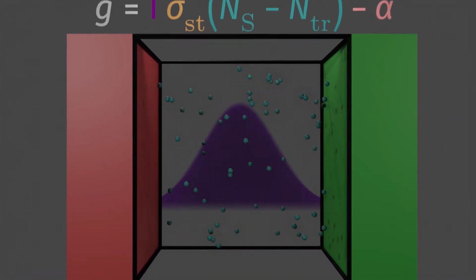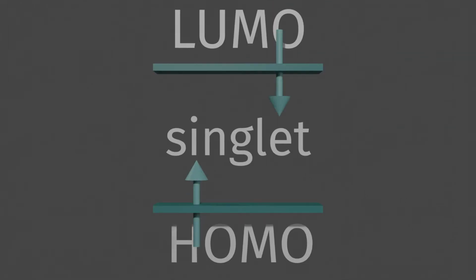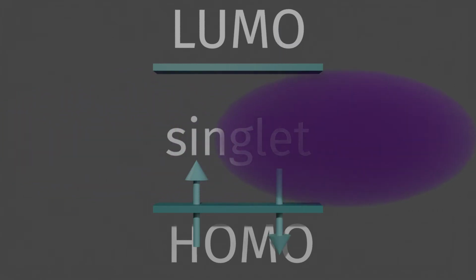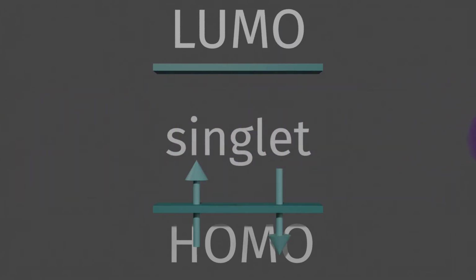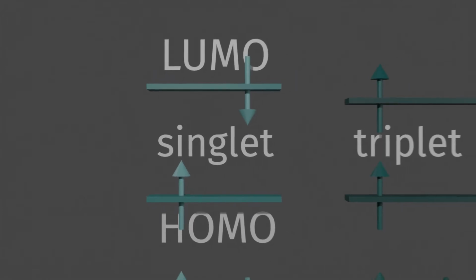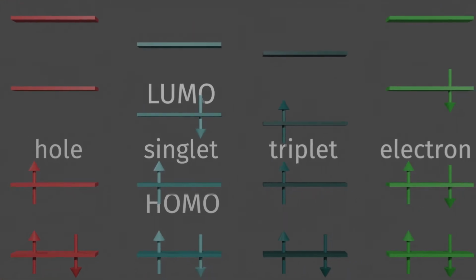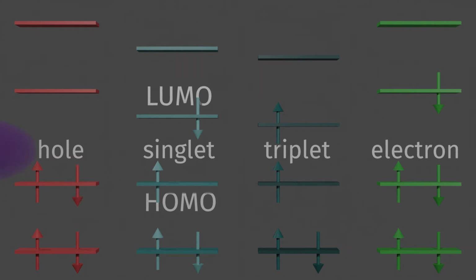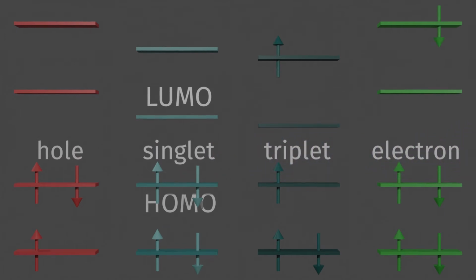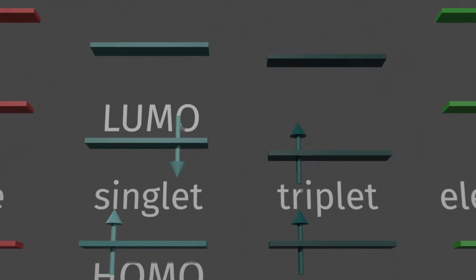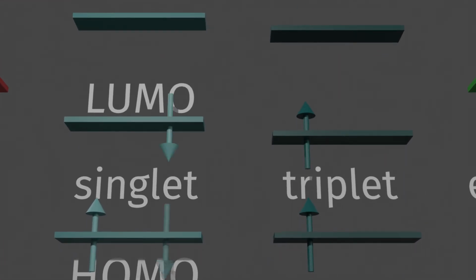If we focus on a molecule, a singlet is composed of 2 electrons with spins out of phase, one in the highest occupied orbital and one in the lowest orbital that would normally be unoccupied. As the lasing mode passes, the singlet can recombine and add to this mode. But we also have triplets and holes and electrons, which can't contribute, but will have allowed transitions that can subtract from the mode. And if this absorption is possible, then singlets can be annihilated by resonantly transferring their energy.